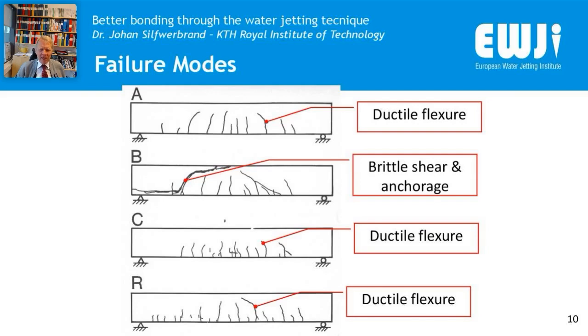So we received a ductile flexure failure on A, and the same on C, where we have the thick overlay, which is going behind the rebars. And then also for the reference, we received the ductile flexure failure. But on the B type, we received the brittle shear and anchorage failure. As you can see, the horizontal crack on the left-hand side of the B beams. And that we always want to avoid, the brittle failure, because that is sudden and it is more dangerous than the ductile failure. And remember, in the B beam, we had a coinciding reinforcement and interface plane.